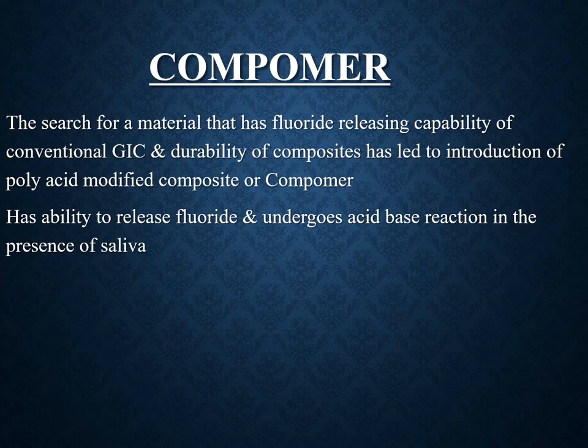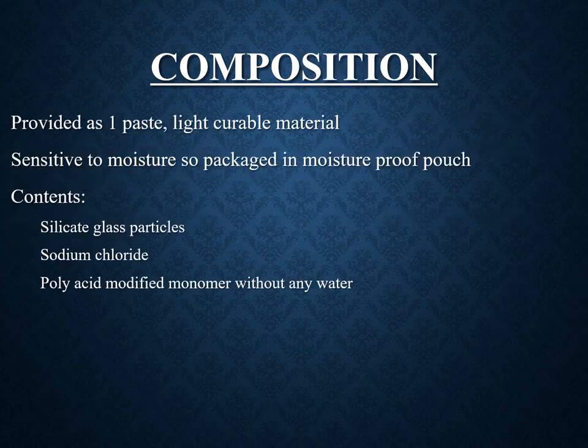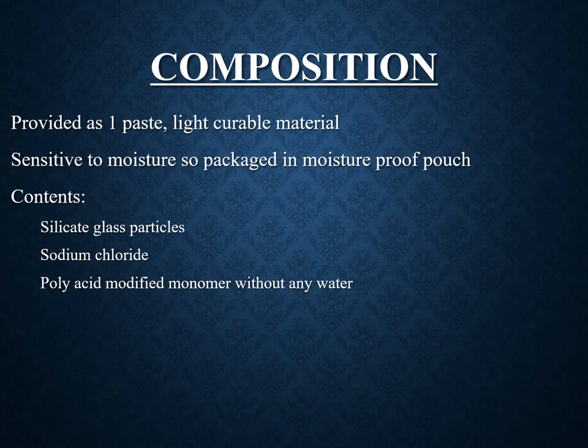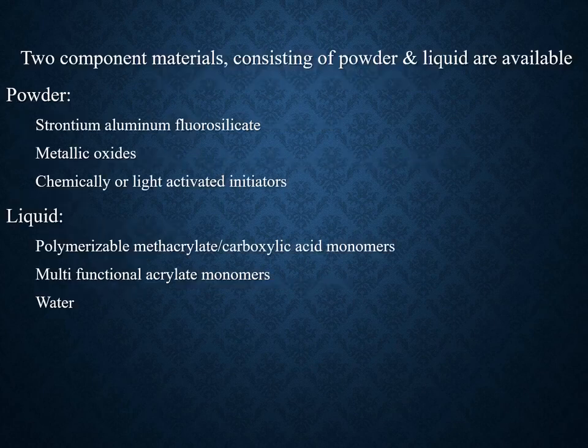Compomers — the search for a material with the fluoride-releasing capability of conventional GIC and the durability of composites led to poly acid-modified composite, or compomers. They have the ability to release fluoride and undergo acid-base reaction in the presence of saliva. One-paste light-curable compomers are sensitive to moisture and are packaged in moisture-proof pouches; contents include silicate glass particles, sodium fluoride, and poly acid-modified monomer without water. Two-component materials consist of powder and liquid.